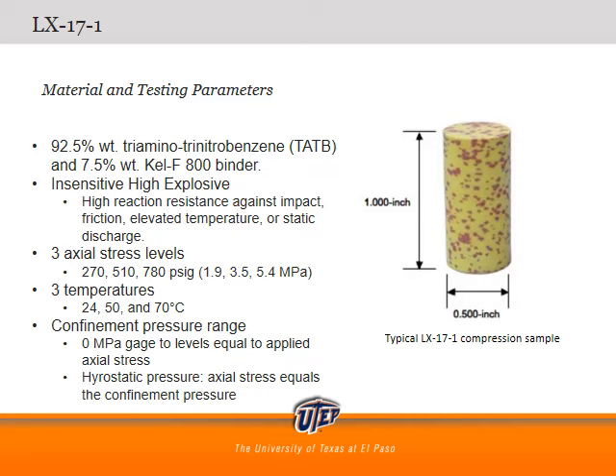For this experiment, it is subjected to 3 axial stress levels, ranging from 270 pounds per square inch gauge to 780 pounds per square inch gauge. It is also subjected to 3 temperatures, 24 degrees Celsius, 50 degrees Celsius, and 70 degrees Celsius. The experiment also ranges the confinement pressure from 0 megapascals in gauge to levels equaling the applied axial stresses, which is also known as hydrostatic pressure when the axial stress equals the confinement pressure.